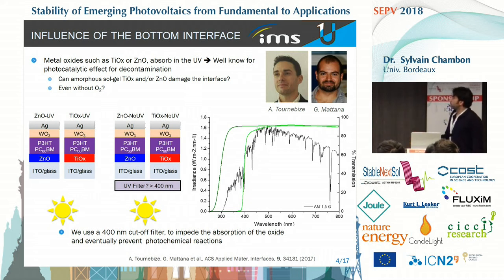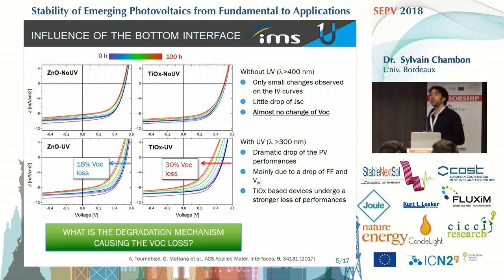We used P3HT:PCBM as active layer, and we studied four kinds of devices: devices with zinc oxide as ETL or titanium oxide, which we aged under the complete solar spectrum, with the UV. And we performed the same aging study, but using a UV filter, cutting the UV below 400 nanometers. We studied the burn-in phase of the degradation, so the first 100 hours.